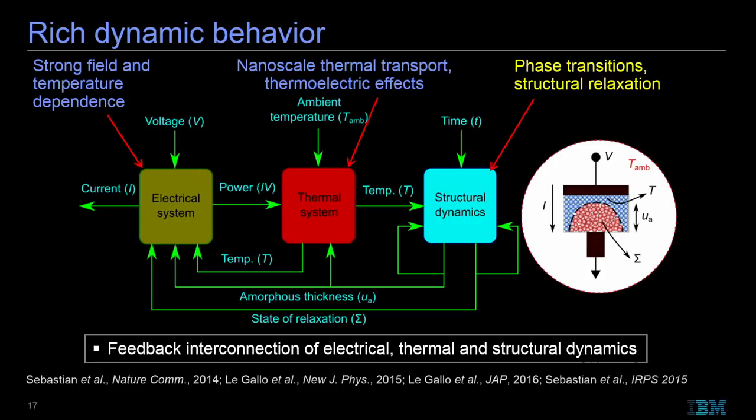Besides the fact that we can store this continuum of resistance states, these devices also have some very rich dynamic behavior. If you look at a PCM device, the PCM dynamics is basically an intricate feedback interconnection of electrical, thermal, and structural dynamics. So it has a strong field and temperature dependence. There is a very interesting thermal system there.